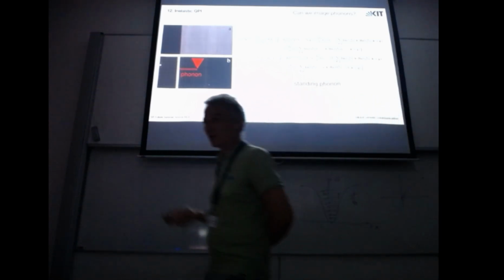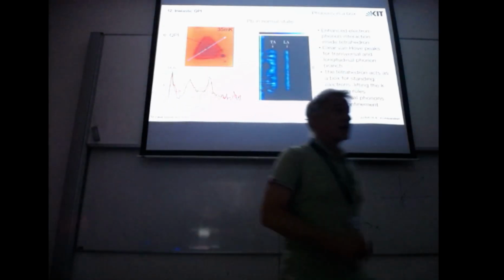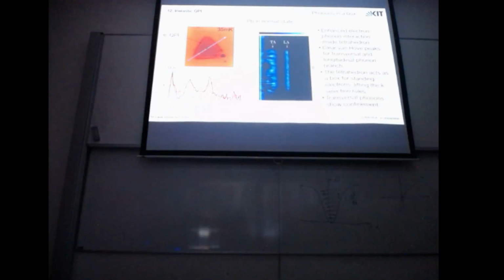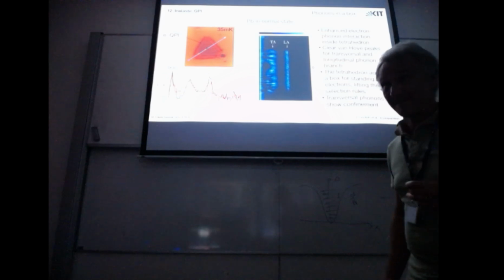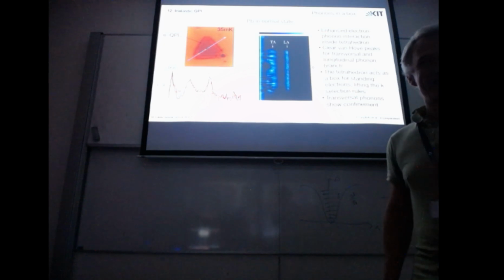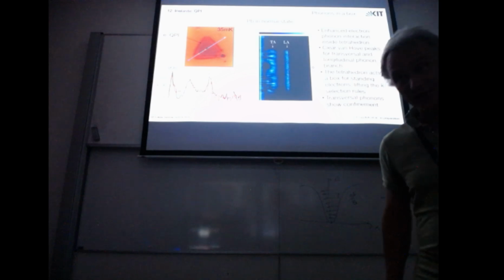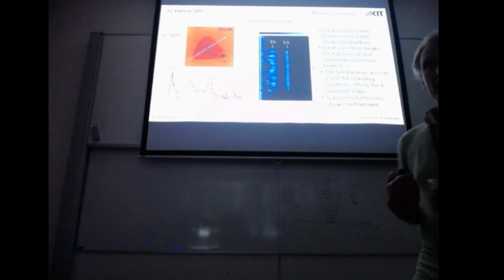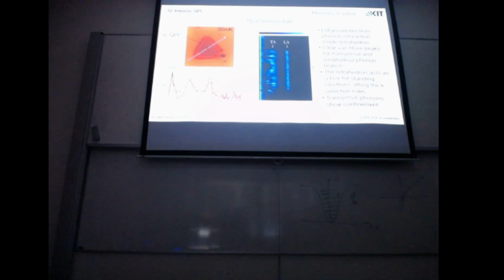If we see it, we have neutron scattering with STM, locally resolved. Now our samples are infinitely extended. It's not a good thing. We need a defect. Well, let's take our defect and measure the differential conductance. Yes, sorry. You can actually create those defects? Yes, but they are not controllable. We take the sample in a hot state and put it into the cold state, so they get a little shock. And they form this kind of inhomogeneity, and then you just find that. Okay. So this is our image.